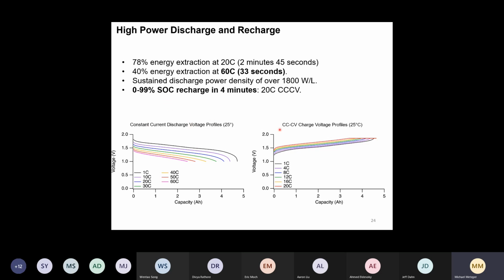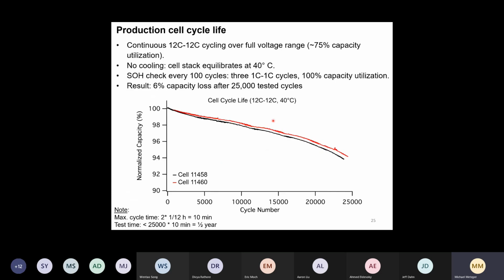And they can also be fast charged in about 4 minutes or so at 20 C. So you have like 3 minutes for the constant current step, and then maybe another minute in this voltage hold here for the red curve, which is 20 C. Sorry, I might have said C/20, of course, 20 C to recharge the complete battery, 0 to 99%.